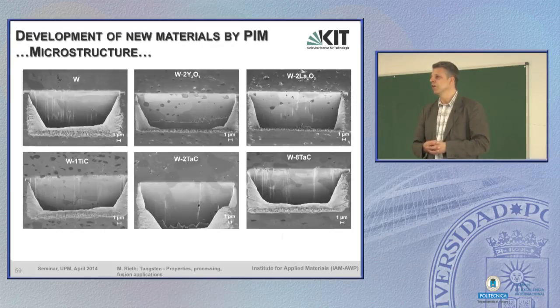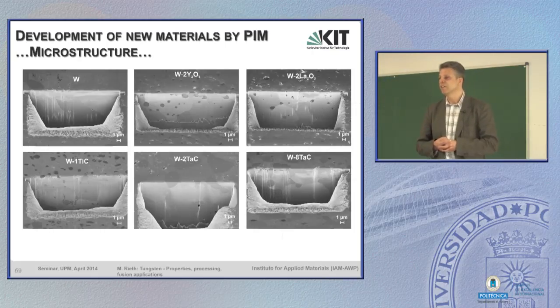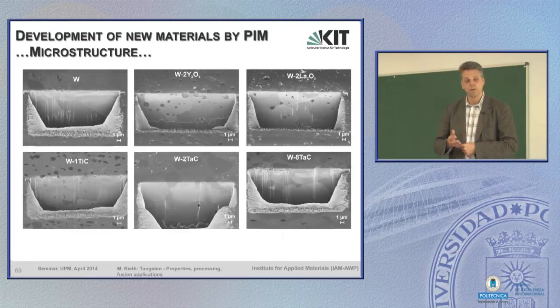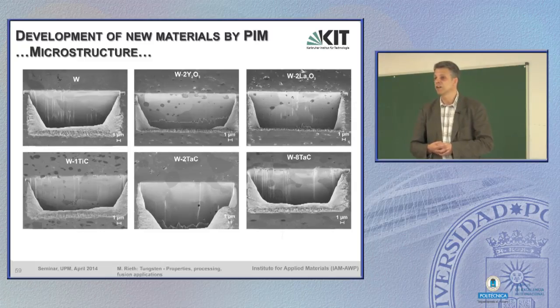This machining tool we have now misused, let's say, also as a rapid development tool for material, because it's rather easy to mix up several tungsten compositions, fabricate a plate or whatever by this machine, and so you can screen rather quickly the effect of alloying. This has been done for pure tungsten as a reference, with yttria, with lanthana, with titanium carbide, tantalum carbide in various percentages. And you see the second phases here. That's the more or less small dots inside the tungsten matrix.